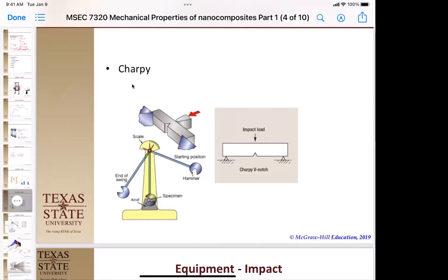Okay, so the thing that's happening here is the amount of time that it's hitting the sample. You have the force over this cross-sectional area, but the rate is much, much higher. In a tensile tester, you can maybe get 30 millimeters a second. Here you're getting like 300 millimeters a second. It depends on the length of the rod as to its actual speed. So it's the rate of strain that changes.